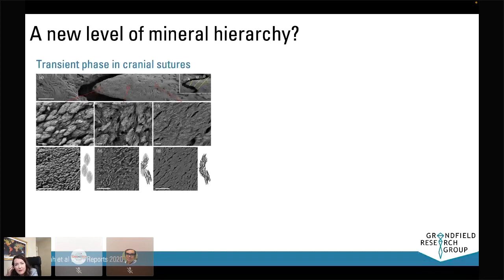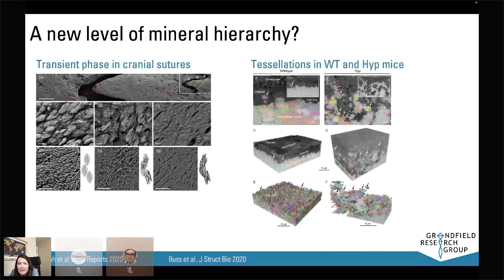Other colleagues at McGill University, the group of Mark McKee and Natalie Reznikov, in the same paper or journal as us, published similar findings, but this time on wild type and hypophosphatemic mice. What they found was that their diseased mice showed a deviation from this ellipsoidal structure and a really disorganized type of mineral packing. So it's quite interesting to see the observations one can make when employing 3-dimensional imaging techniques to see these new features of mineral clustering within bone structure.